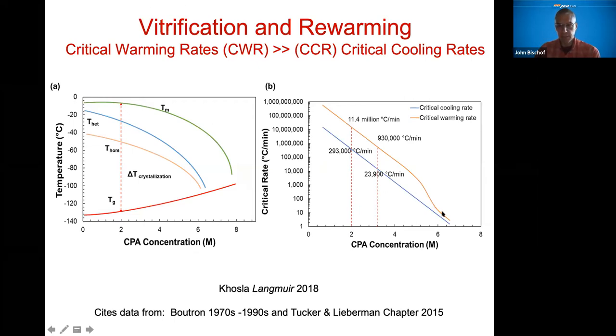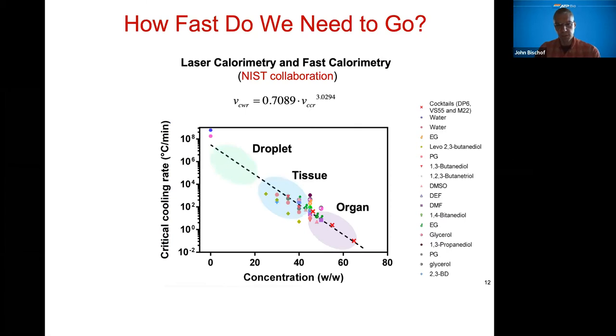And you can see again that the critical warming rates, and this is log scale on Y, and you can see we're getting into some really, really fast rates here that I'll talk a little bit more about. But if you're down here in 2 molar, which will work for some of the smaller systems, you're going to be in the hundreds of thousands of C per minute on the way down, but then you need to be in the tens of millions on the way back up. So these are just giving you some sense of scale and rate. We can also think about this in terms of the size of these systems and the concentration of CPA we might be using or need to use.